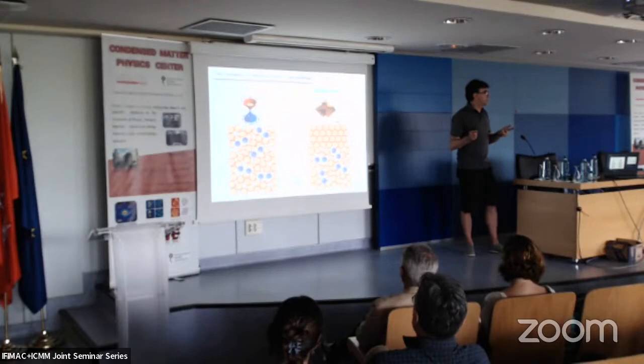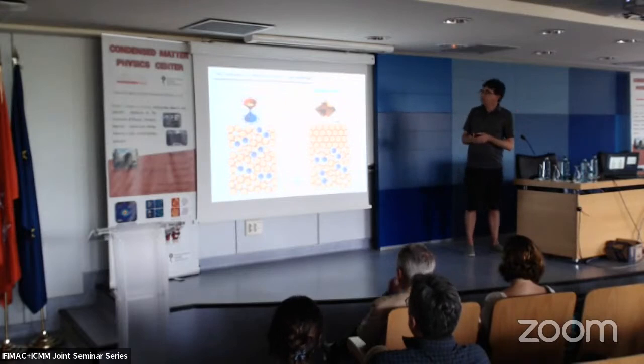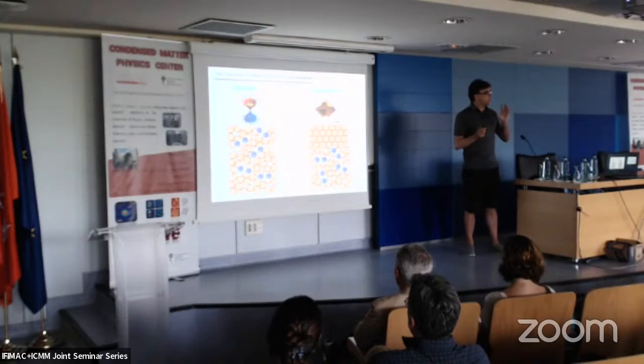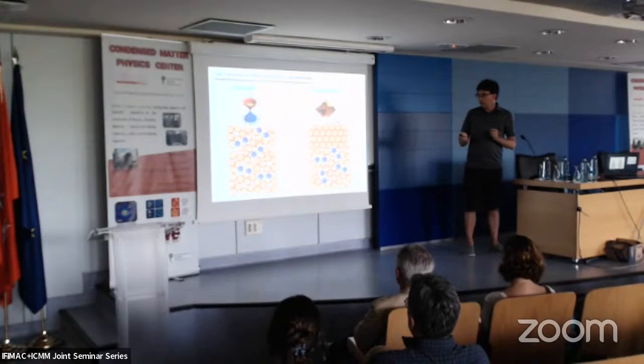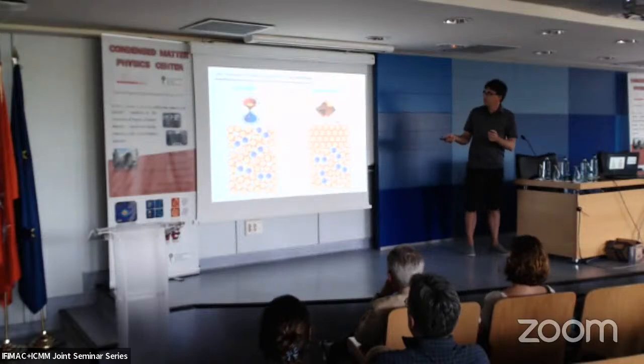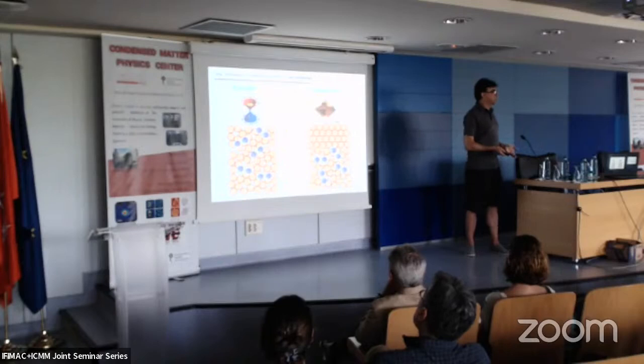We have two scenarios. The best case scenario, the first one, would be, as I said, the combination of the amorphous material containing the topological material of the crystal. In this case, then we expect to have protected Dirac states in coexistence with the superconductivity of the parts. Okay, this is the first scenario.